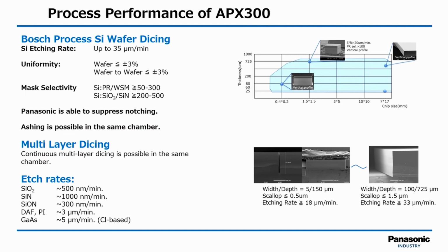So looking at the performance of the APX300, taking the Bosch process silicon dicing example, we can achieve up to 35 micrometers per minute dicing speed. Uniformity is a high priority for us, so on the wafer it's less than 3%, and wafer to wafer we also maintain less than 3%. It's possible for us to suppress notching. So this is very important for almost all of our customers. As soon as we get to the end of the wafer, the bottom of the wafer through dicing, make sure that we don't over-etch or create notching.